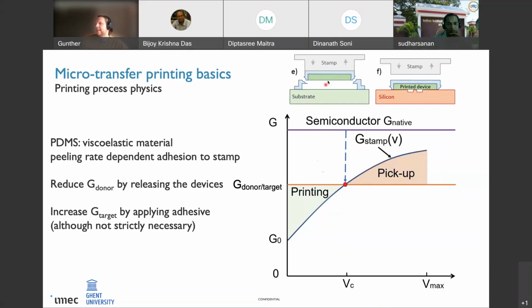So what is now the idea? The idea is that you design your tether structures such that the force or the adhesion between the stamp and the device is stronger than the tethers during the pickup process. So that in that case, the device remains attached to the stamp and you break the tethers. While in the case of the printing, you actually use a very low peeling rate, such that the adhesion between the stamp and the device is weak, such that the device remains attached to the silicon target wafer. So by optimizing that, you can get a high yield pickup and printing process.